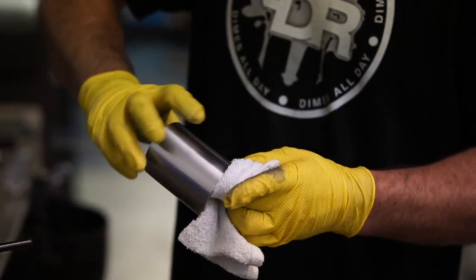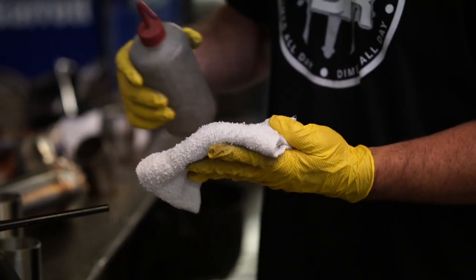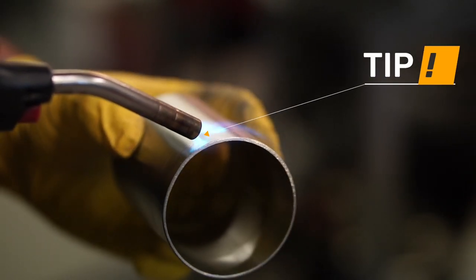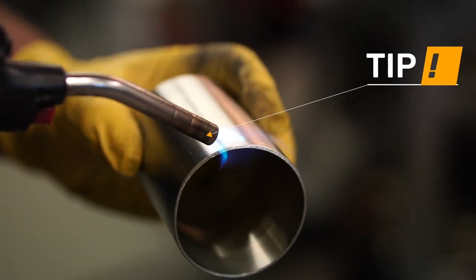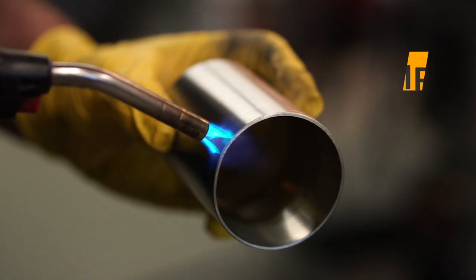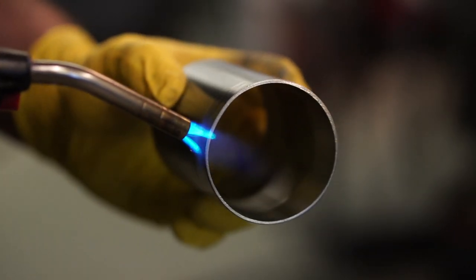Acetone is key. Clean the part really well, no fingerprints. Make sure you're prepping the entire piece of material. And if you do use a rag that is not lint free you can always take off the fibers by just using a propane torch to hit the lip of the part that might have the contaminants.